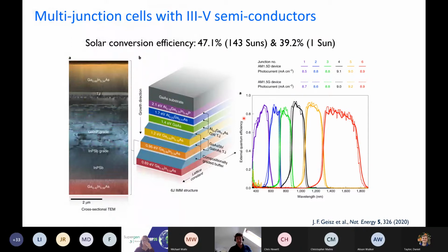This, as I mentioned, is not a new technology, and this has been developed a lot in III-V semiconductors and specifically for concentrator PV in the past. And the world record efficiency for a solar cell is actually 39.2% under one sun terrestrial sunlight, up to close to 50% under concentrated sunlight. And this is the spectral response and the structure of such a cell. So this shows it's physically possible to make really efficient cells through the multi-junction approach.